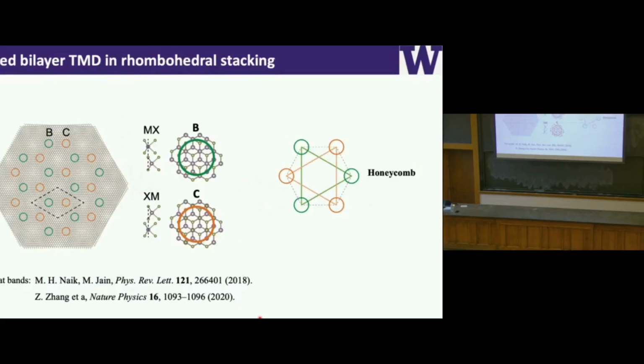Okay. What we do is we stack these monolayer TMDs on top of one another with a little twist angle. Then we form these homobilayer moiré superlattices. Within these single unit cells, there are two high symmetry points, as I highlight here in two different colors. One high symmetry point we call B, which is metal on top of chalcogen. Okay, so metal on top.